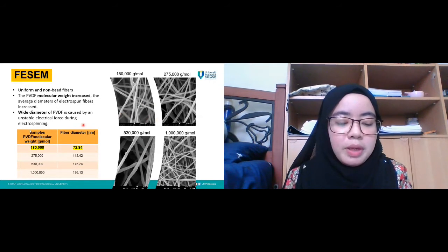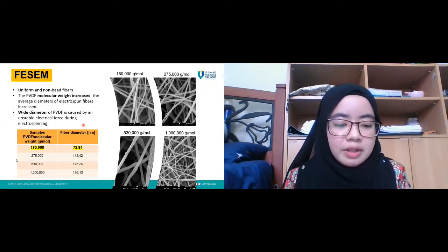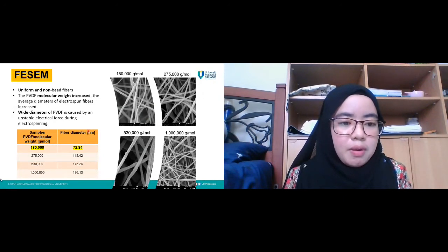From the FESEM image, the average diameter increased when the molecular weight of PVDF increased. The PVDF of 530,000 grams per mole displays the widest diameter because of unstable electrical force during electrospinning.